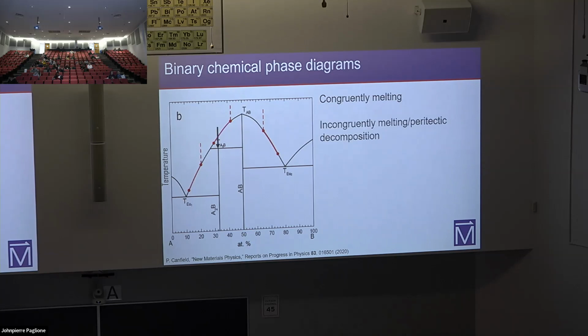Okay, so we can go on to another one. Now what about these guys that don't make it all the way up to the melt? This A2B phase present here gets cut off by this line. This is something called an incongruently melting, or peritectic, phase. There are a few ways to think about this. One is that if I combine these elements A and B, heat them up into the melt, and then drop down here, I'm going to get a mess. When I enter this phase region, I'm going to get a combination of some crystalline phases that will drop out depending on how fast I come through here. You get some A2B and some AB, as well as a mixed-up alloy of A and B.